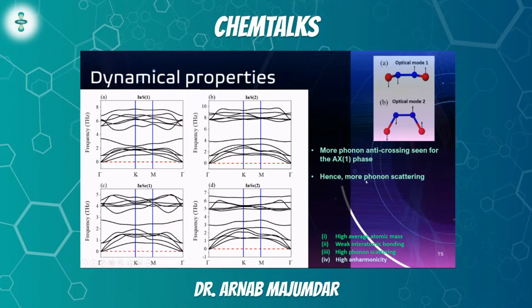Now, what does phonon anti-crossing imply? It means that there will be more scattering. There'll be more phonon hybridization and there'll be more scattering. That's exactly what we were looking for. That means compared to AX2, our structure AX1 has more phonon scattering. So 3 of the criteria have now been fulfilled.